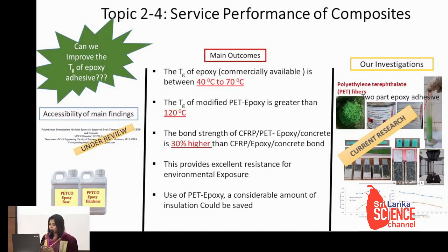That works very well even under ambient condition as well as fire condition. It can raise the TG of the bond, normally 40 to 70 degrees. With that adhesive, we could raise it up to 120 degrees. That's a very good achievement. And also under ambient condition, we noted 30% higher strength than the normal bond. So this provides excellent resistance, that means a very stable structure with good performance. Not only that, if you are applying this for buildings, we can save a sufficient amount of insulation, which again will result in a low cost project.